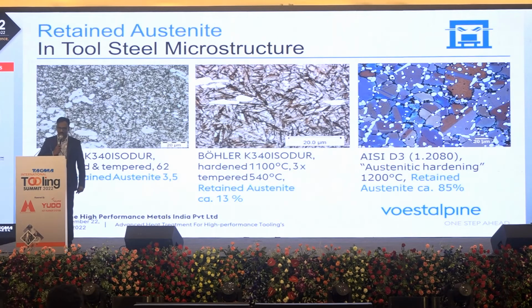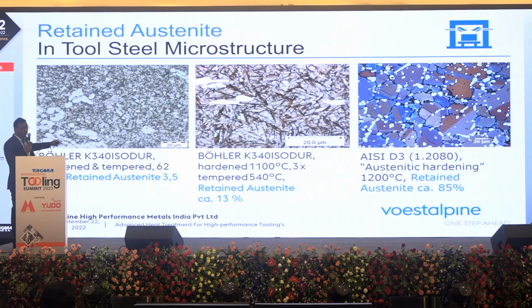Now, the heat treatment does not get completed at room temperature. And we also know that retained austenite is a multifarious component which is detrimental for the application of tool steels or tooling applications. For an example, just for your understanding, if you see the picture, BÖHLER K340, which has been fairly heat treated at the recommended temperatures, the hardness was 62 HRC. The retained austenite is close to 3.5. This is the proper heat treatment, what I said.